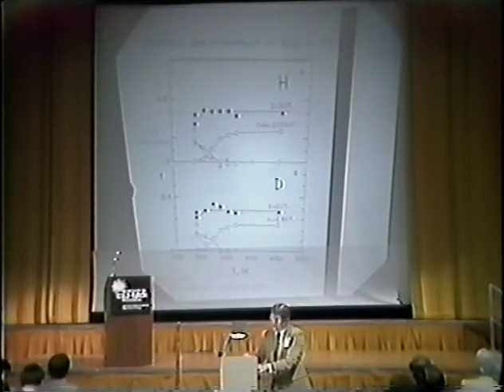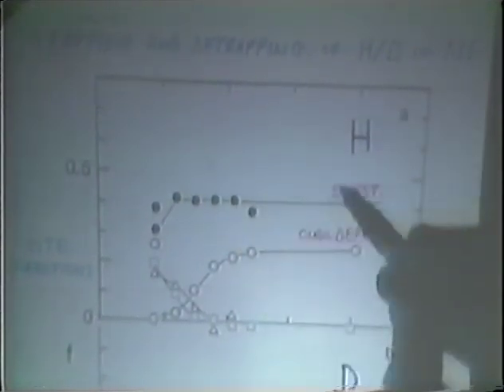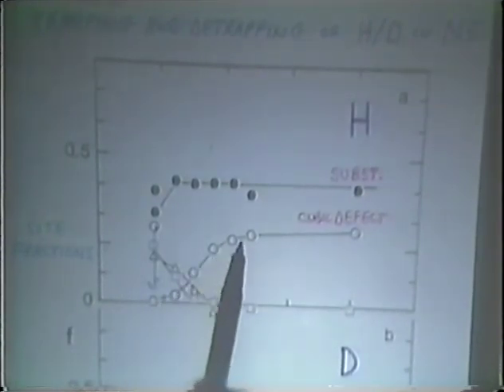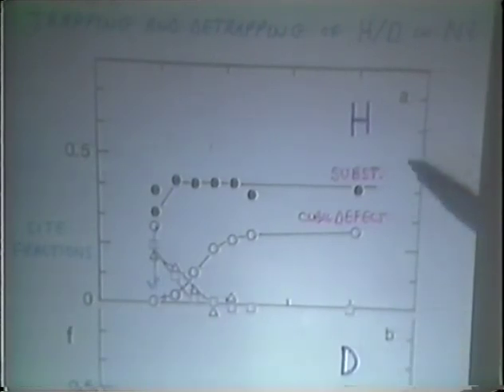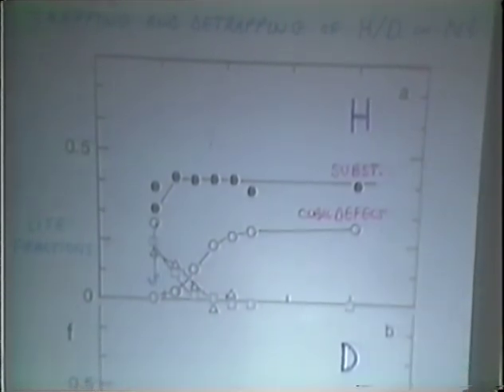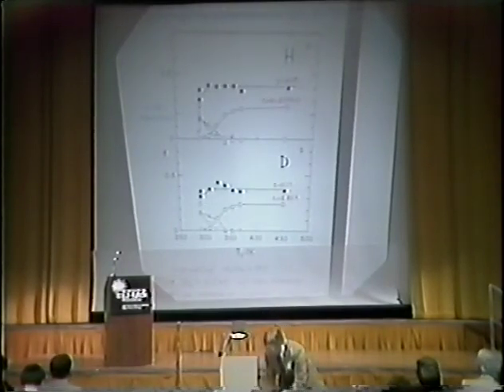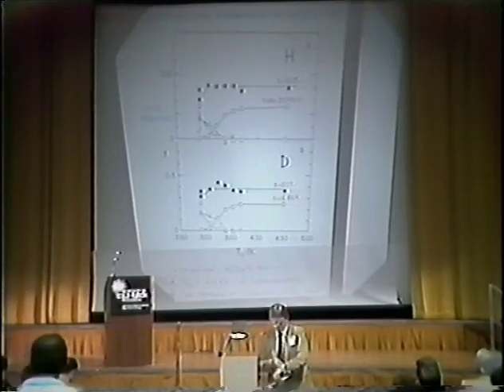In this figure is shown the amplitudes of those signals as a function of annealing temperature. After hydrogenating the complex, the cubic defect fraction falls to 0, and then it slowly recovers as we anneal into the temperature range from 300 to 350 K. We get the same qualitative results for hydrogen and for deuterium. Now, I should say that this kind of detrapping behavior centered around 350 K has been observed in very many samples.